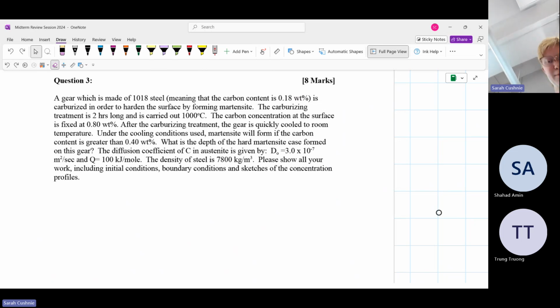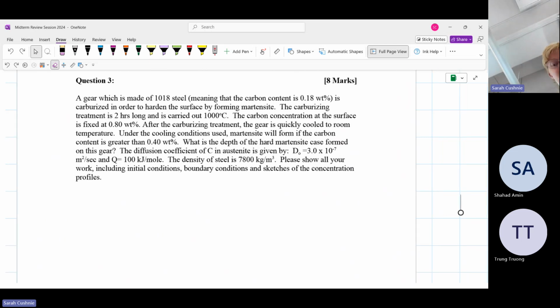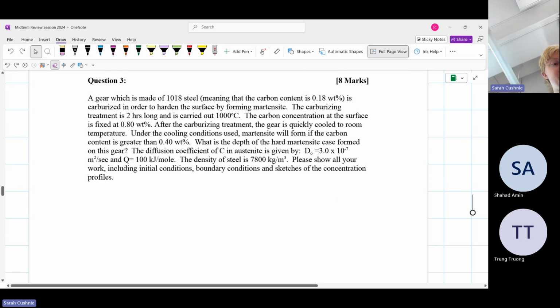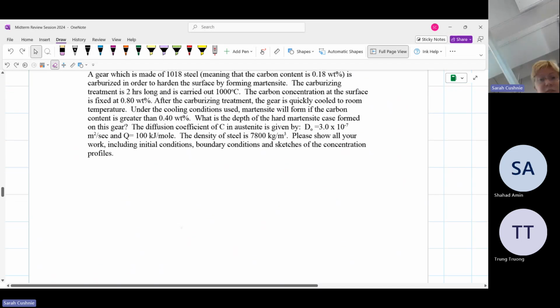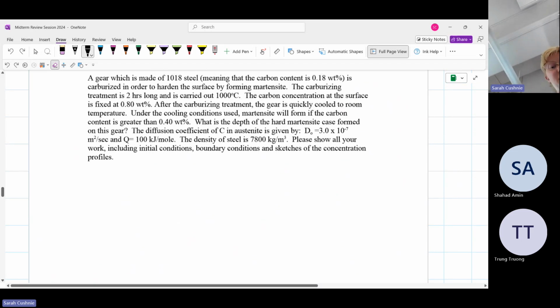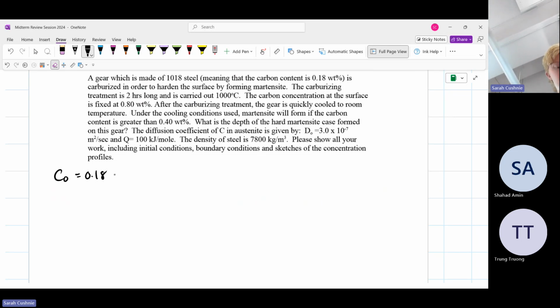So this is a much more calculation heavy question. I found all of the numbers overwhelming as opposed to the situation. So I started this by just writing out all of my variables, because I was like, wow, that is a lot of things. I'm just going to go through the question and write things as I see them. So we start with the initial gear with some sort of carbon content. That's our initial carbon content, so C naught is equal to 0.18 weight percent. And then the carburizing treatment is done for 2 hours at some temperature. So I'm going to say t is equal to 2 hours.